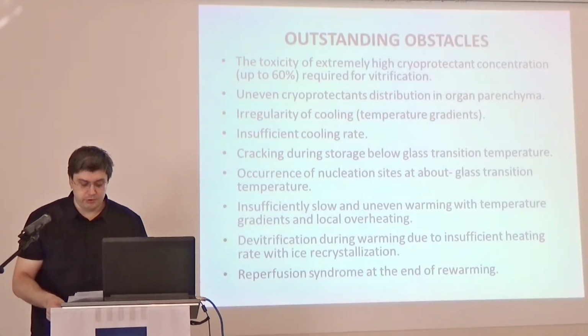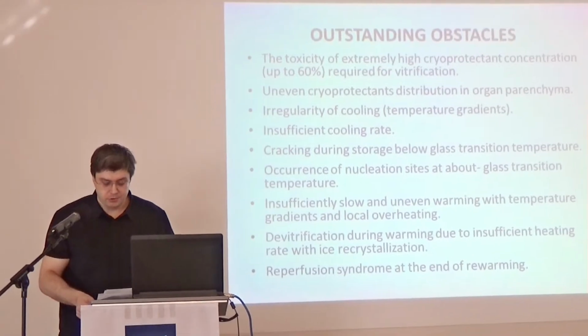Ice formation during warming happens faster than during cooling because ice nucleation occurs at lower temperatures than ice growth. This nucleation leads to extensive ice growth at warmer temperatures. That's why the so-called critical warming rates are typically 2 or more orders of magnitude greater than critical cooling rates.